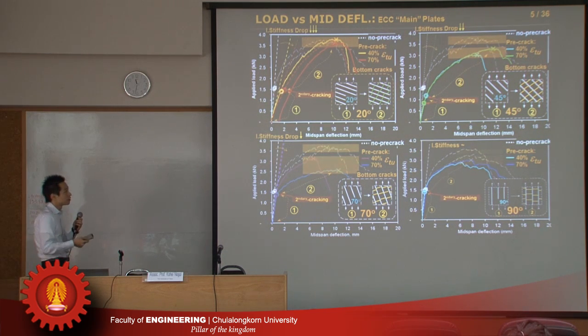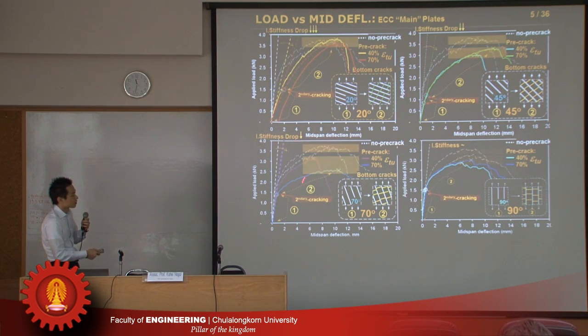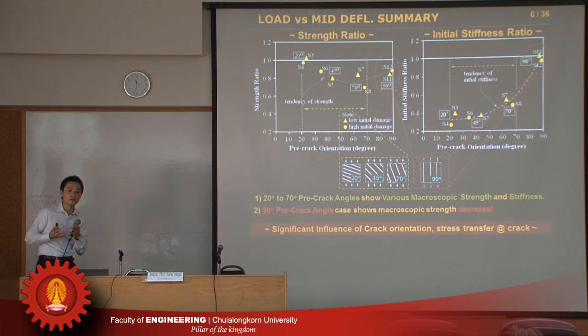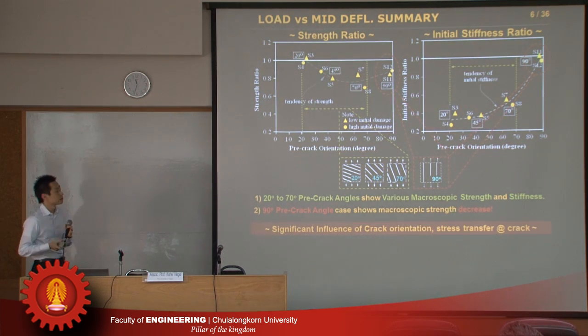Similar strength is observed. But by increasing the angle from 20 to 45, yes, initial stiffness decreases a little bit, and strength also decreases a little bit. And yes, 70 also. But in the case of 70, the reduction is less on the initial stiffness, but still the strength reduces. And for 90 degrees, we have almost no reduction of the stiffness, and still we have the strength reduction. So due to the initial damage angle, the secondary loading result changes dramatically. So it's because of the initial damage that may relate to the shear performance of the initial cracking.